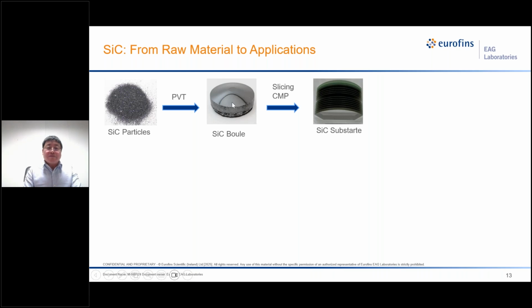The silicon carbide has super hardness. It's almost the same as diamond. So the slicing and polishing will be a problem. Generally for a boule, this takes a week to grow, and it will have something like 40 to 50 substrates from each boule.